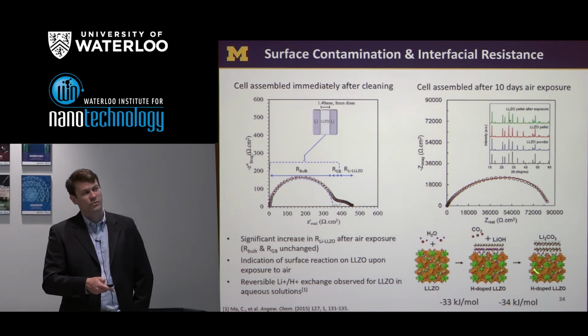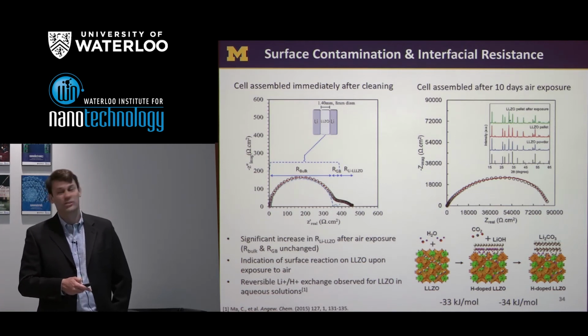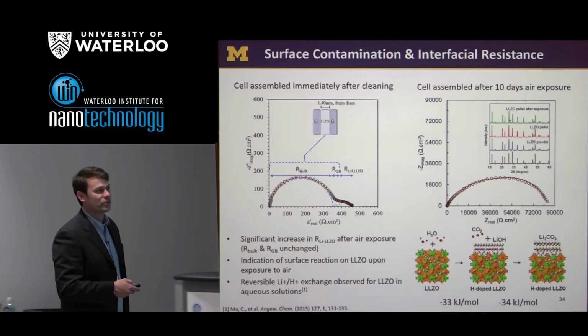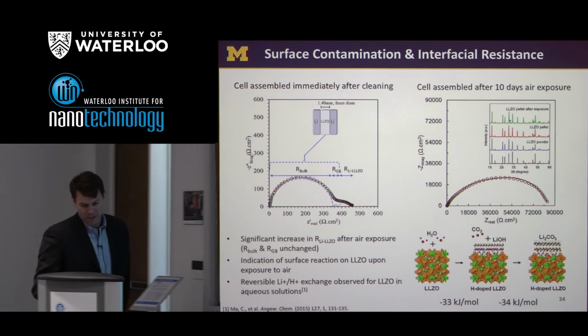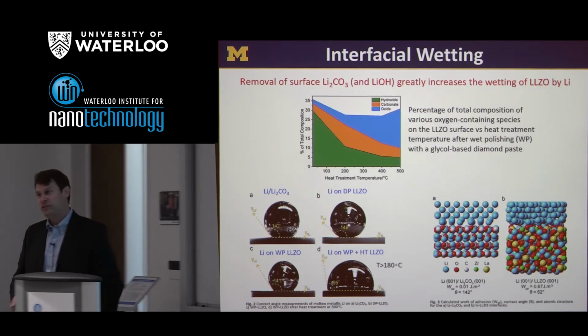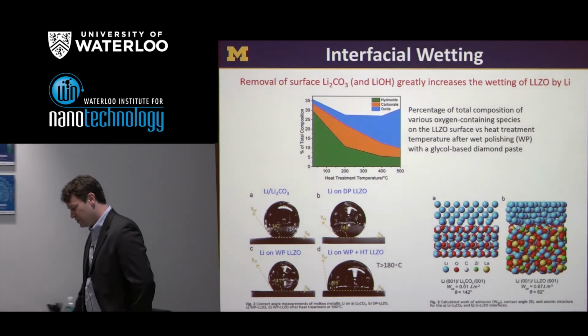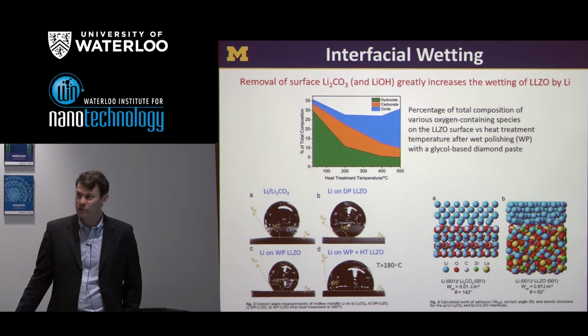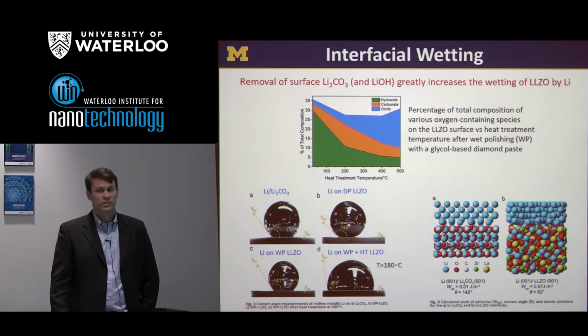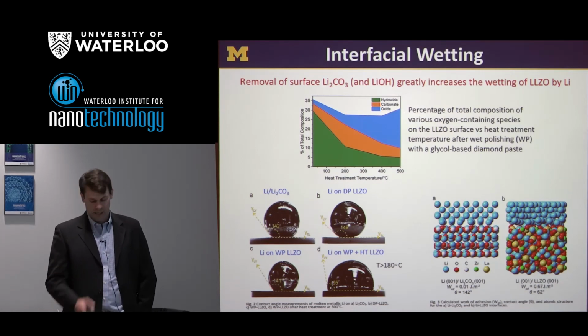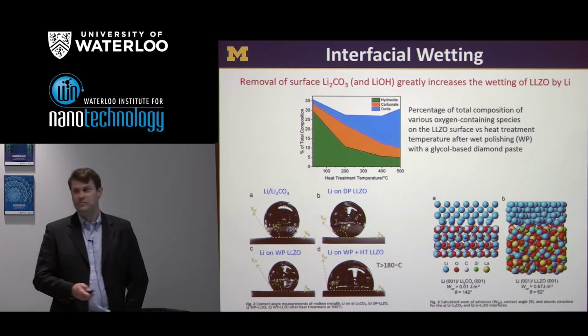And so this formation of this skin of carbonate and hydroxide is hypothesized to be the reason why this large interfacial resistance exists. And so people have, of course, already noticed this. For example, Eric Wachsman's group has developed techniques for coating the LLZO with atomic layer deposition to try and minimize this reactivity with air. But what I'll tell you about is that you don't actually need a coating.